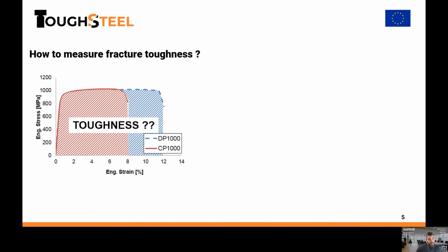Here, the first important message that we want to make is that fracture toughness cannot be estimated from tensile properties. It is often assumed that steels, or materials in general, with greater elongation or greater area under the stress-strain curve, or for example the greater UTS by total elongation product, which is usually also used as a toughness indicator, are related to the fracture toughness of the material, but this is not true. We will see that later also. But the important message is that we have to forget about this approach of trying to estimate fracture toughness properties from the tensile properties.